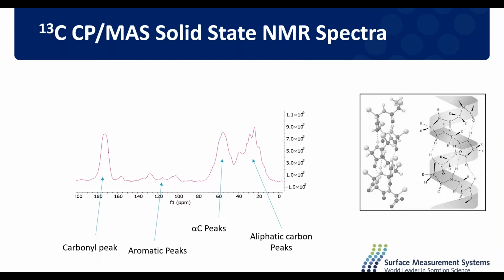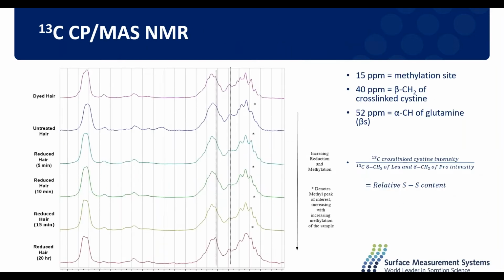So clearly this is quite a lot of information, and we performed this experiment for all of our hair samples so that we could examine what changes had been incurred due to damage. And here are the spectra. We've got our dyed hair sample on top, untreated hair here in blue, and then our reduced hair samples, increasing in reduction and methylation going down. We reduced hair for 5, 10, 15, and 20 hours. Sorry, 5, 10, 15 minutes, and then 20 hours.